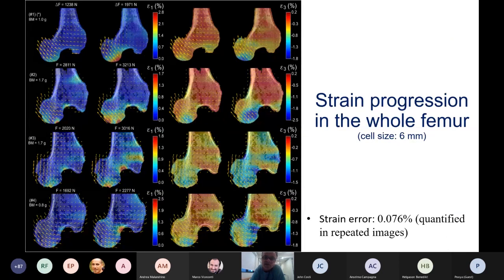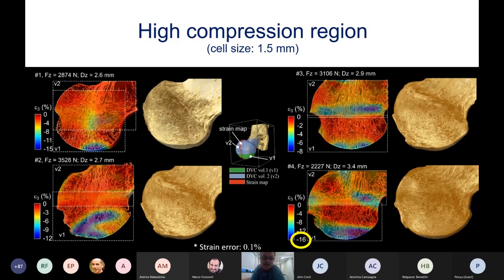Looking at the strains in the entire bone, we see here the DVC calculation using a cell size of 6 millimeters. We are identifying some local region on the proximal head where we have peak tension and compression level. If we zoom into those regions, with a cell size smaller than 1.5 millimeters, we are seeing much higher compression, ranging from 8 to 16% compression. In those regions of high compression, fracture did not occur.